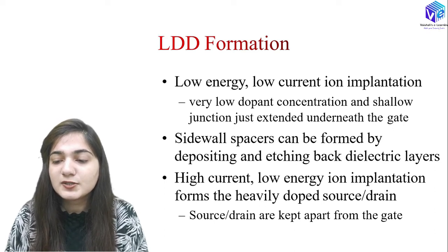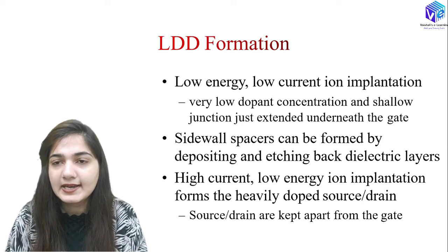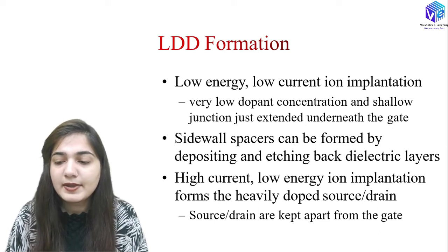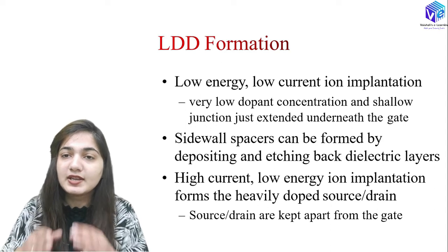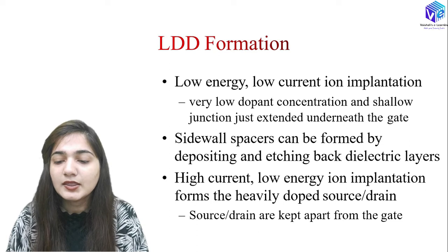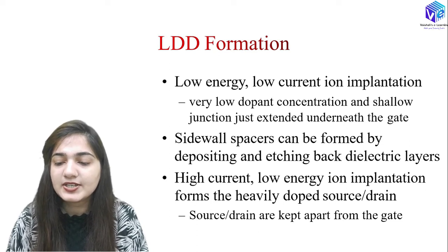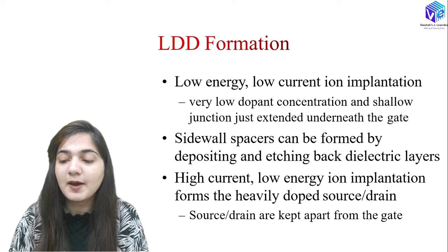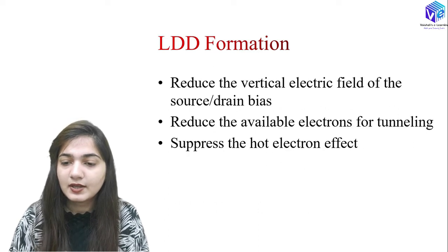Sidewall spacers can be formed by the deposition and etching back of dielectric layers. We can use the deposition and then etch back the extra layers for the sidewall spacer formation. Now high current and low energy ion implantation forms the heavily doped source and drain, and the source and drain are kept apart from the gate.